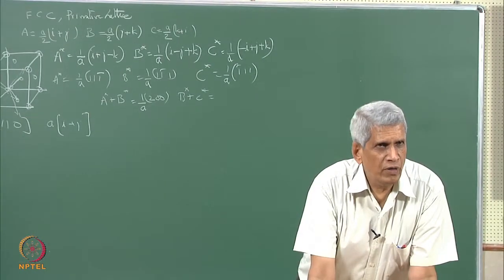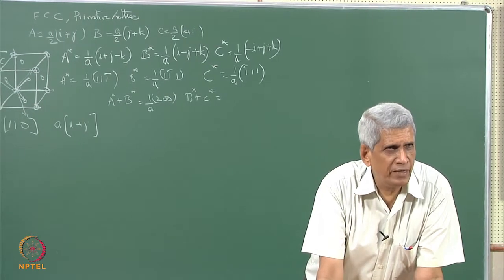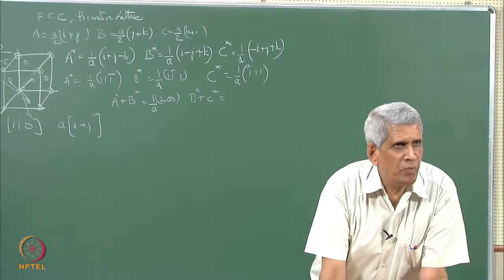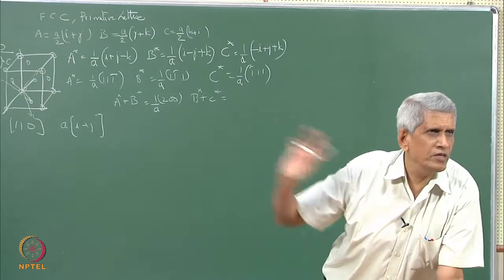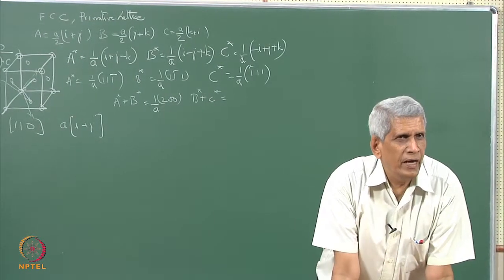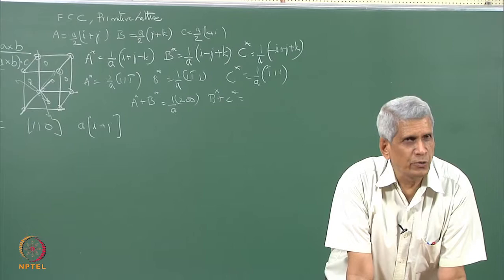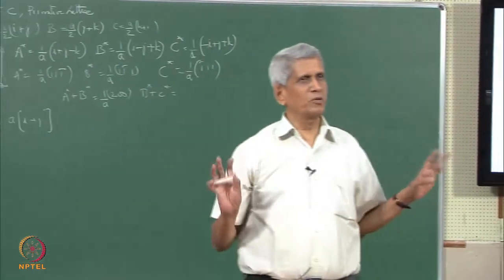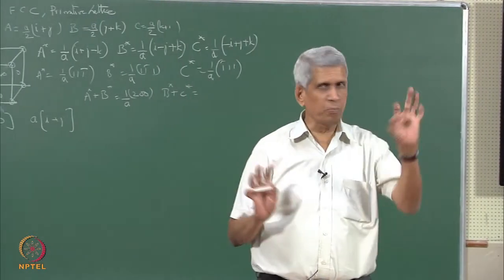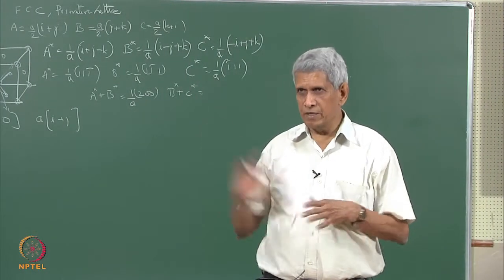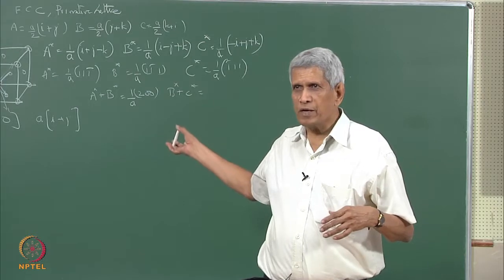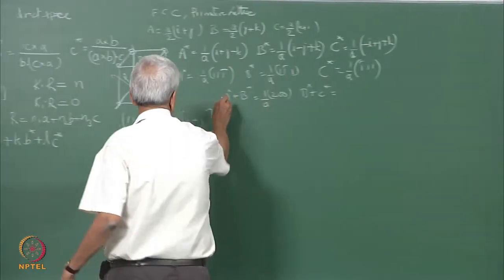So, what I wanted to emphasize at this point is that the reciprocal lattice point which has been constructed using this relation automatically takes care of the extinction rules if we construct it with respect to the primitive lattice. That is all which has to be done. That is one important point. Is it clear? Okay, 100 will not come in this.